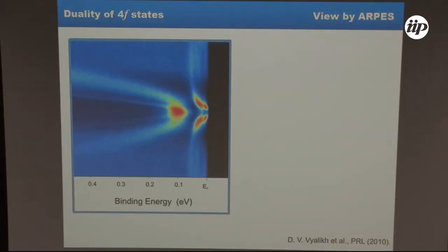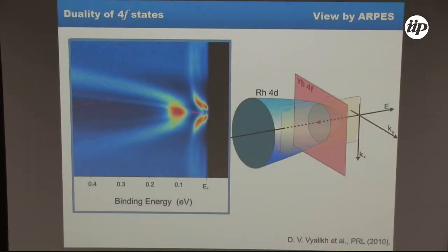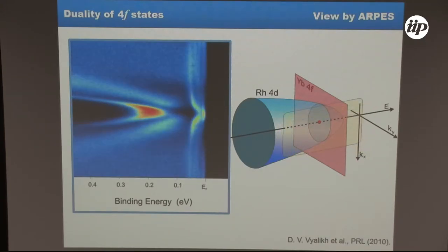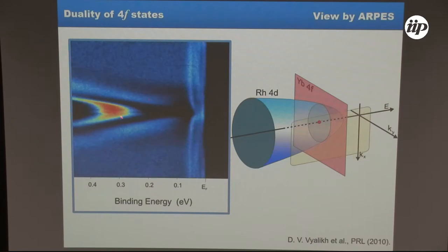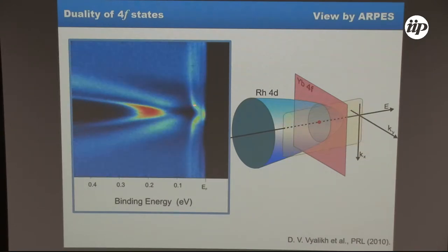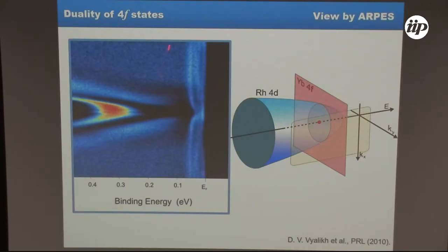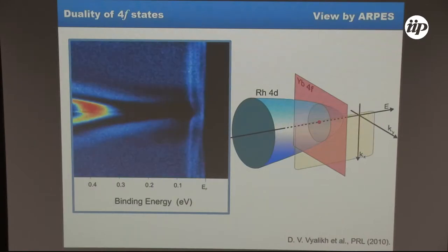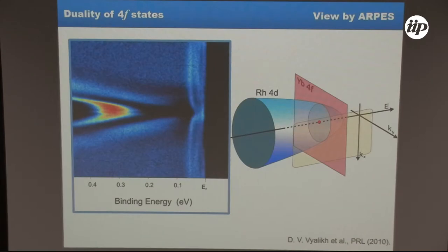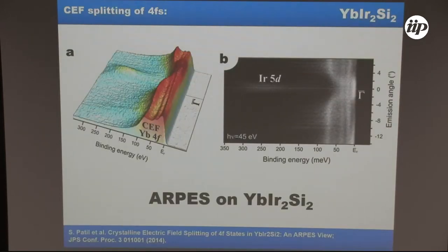I would like to show — and maybe most of you have already seen it — what to me is a really good-looking example demonstrating how the f-states are coupled with linear bands. We took a few images by photoemission and combined them to create an animation giving a good view of how the states start to couple. You can see when this band comes closer and closer to the Fermi energy it starts to hybridize — in the gamma point region the f-states reveal band-like behavior pushing above the Fermi energy, and apparently the Fermi surface has a strong f-contribution. However, away from the gamma point you can see monotonic behavior, demonstrating a kind of dual nature of the f-states.